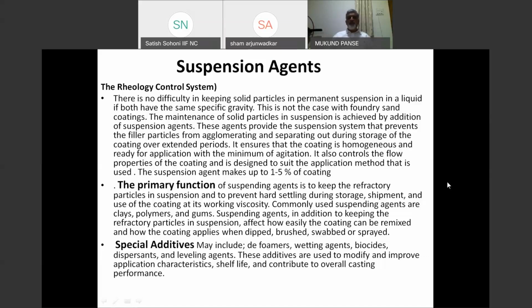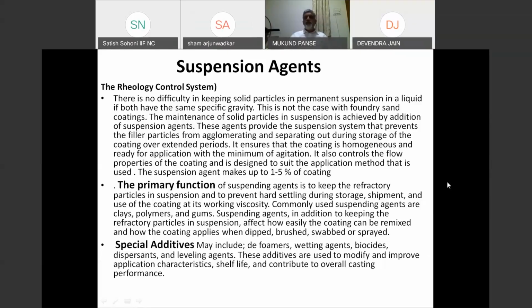The agent provides a suspension system, preventing the filler particles from agglomerating and separating out during stationary storage over an extended period. They are normally required at 1 to 5%. As we have said, 50 to 70% is refractory only, 1 to 5% is the suspension agent, and the balance is mainly the carrier. The suspension agent should ensure that a homogeneous coat is available most of the time with minor stirring.